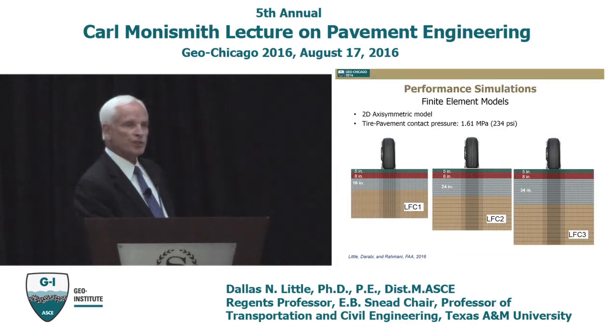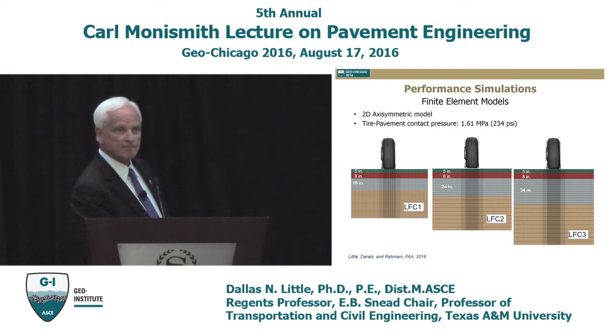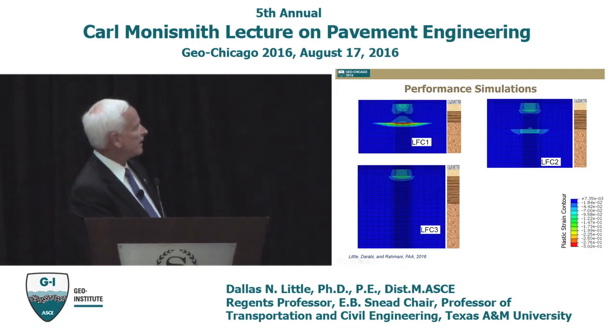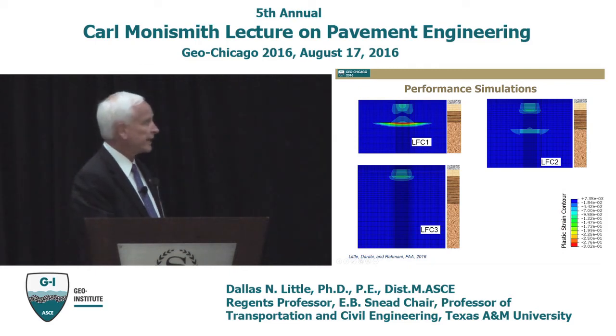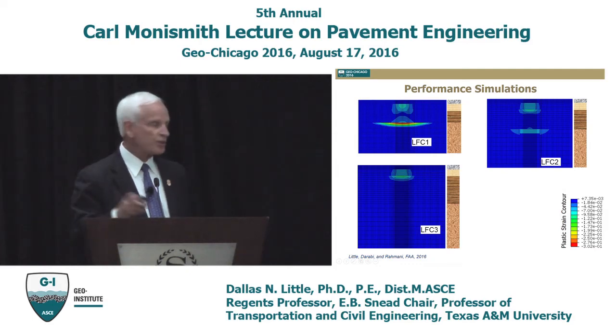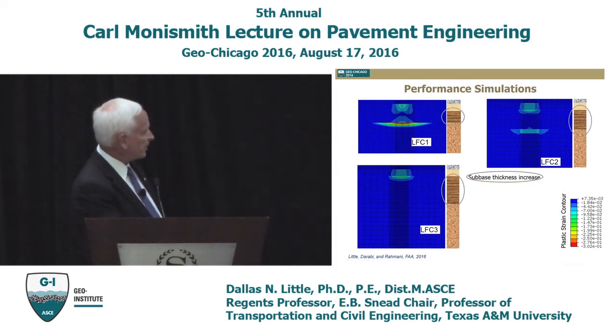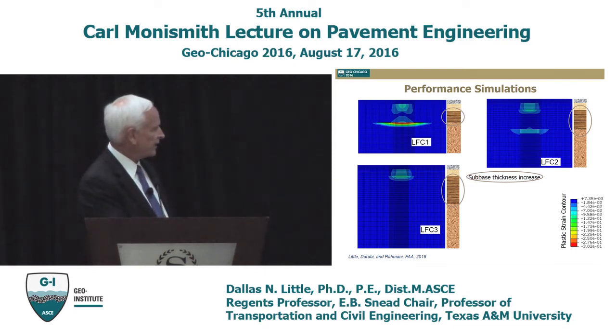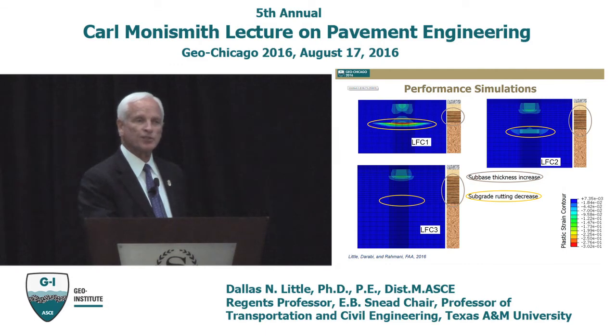We tried to use this approach to actually calculate the rut depths that were occurring in 3 sections, LFC 1, LFC 2, and LFC 3. The only difference among the 3 sections is in all 3 sections the asphalt layer and the base layer are the same thickness and the same material. So there's no difference there. The only difference is the thickness of the subbase, and all the subbase is the same material. So just the thickness of the subbase. And as you would expect, you're going to get more rutting in LFC 1 than you will in 2 or 3 because of the higher stresses there. And that's exactly what we saw.